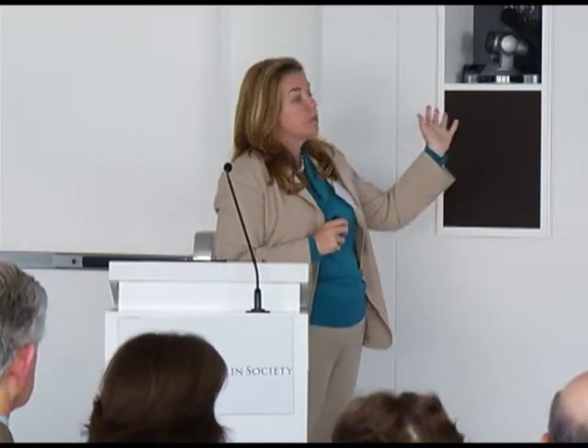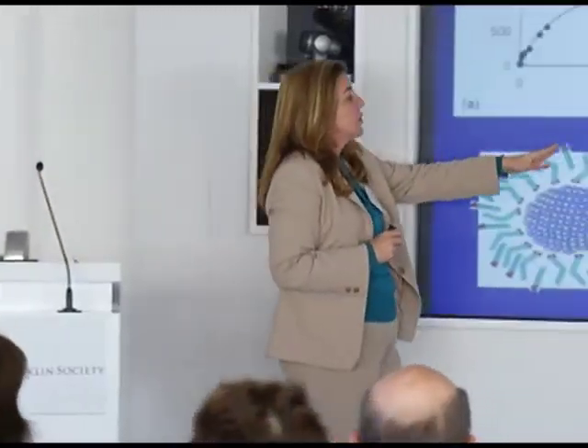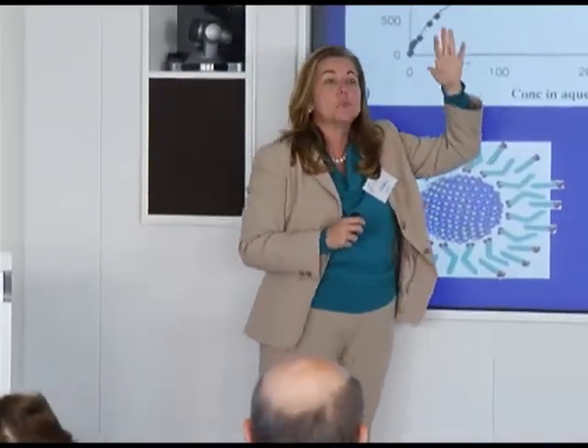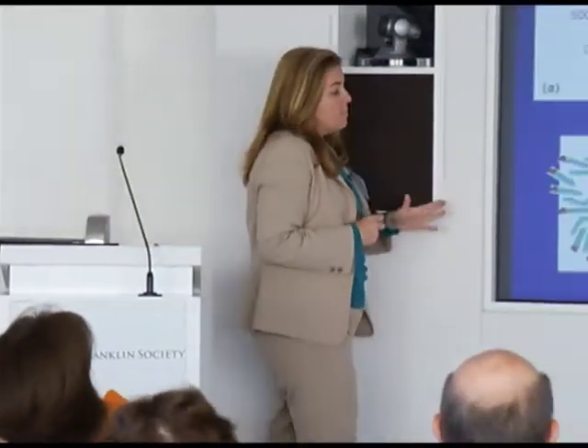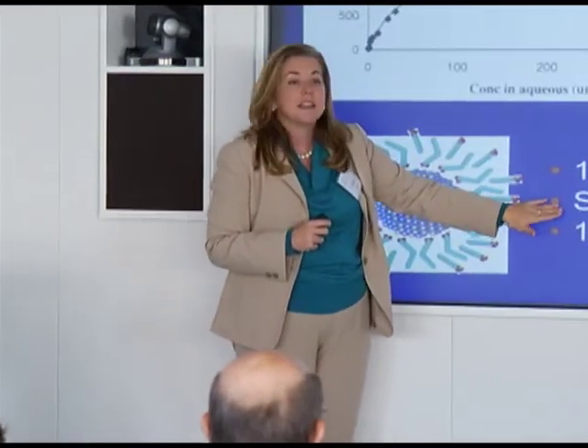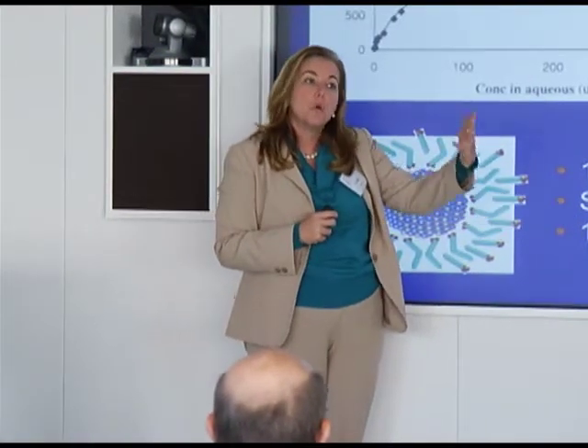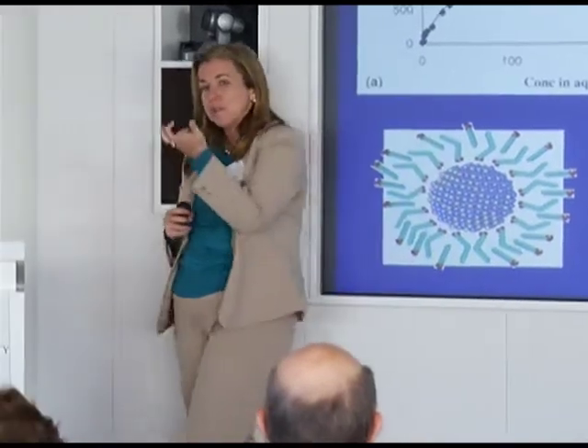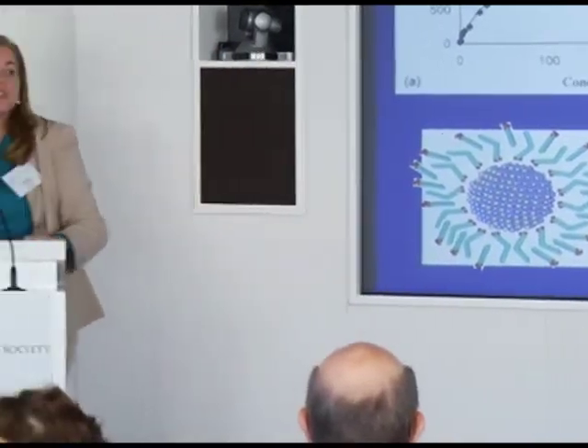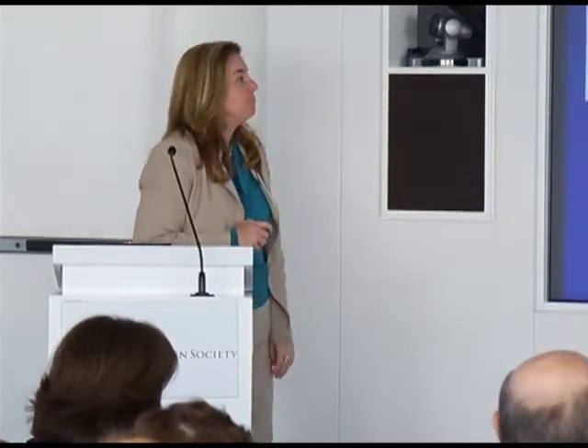These are some examples of absorption curves where you expose the materials to arsenic and you watch how much gets absorbed. There's some very interesting chemistry here. But to cut to the chase, it worked as we expected. We found absorption capacities in excess of 12 weight%. So in 1 gram of one of my iron oxide powders, we could get 120 milligrams of arsenic, which is a really, really high number and starts to look practical in some ways.